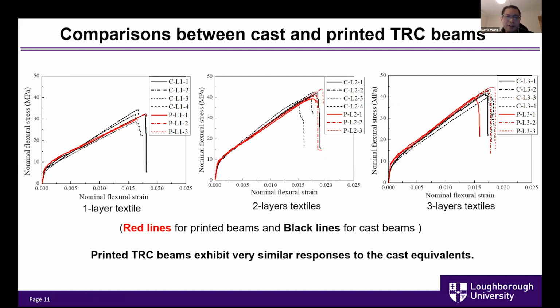These three figures, I think, are very encouraging. We did some comparisons between the cast and printed TRC beams, and it's very encouraging to see that the printed TRC beams exhibit very similar flexural responses as compared to the cast beams. So it means that there is no significant influence caused by the printing process if the printing process is well controlled.